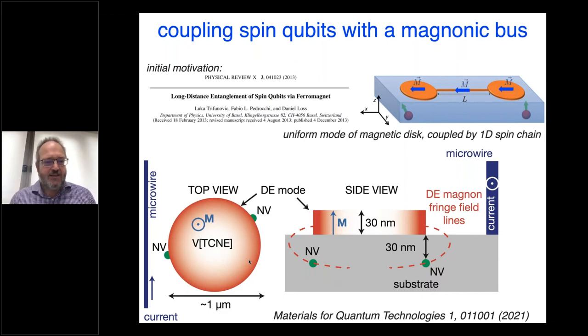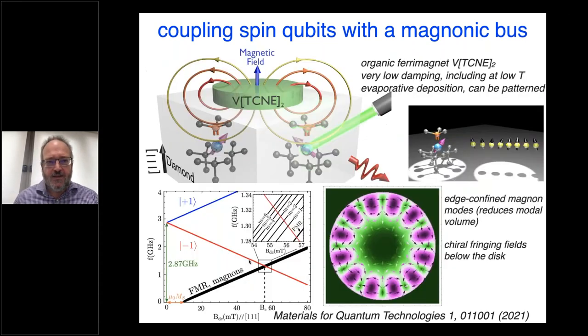So we have a disk of magnetic material with the magnetization out of plane, and that allows us to look at internal spin wave modes of the disk. In the initial proposal, these were all uniform modes. Here we're looking at modes that have internal structure. The reason for that is to take advantage of the lower mode volume for the spin waves in these systems. So in a disk with magnetization out of plane, like below, there are modes that exist along the edge of the disk called Damon-Eshbach modes that are going to be more localized there and therefore have lower mode volume. And when you want to do coupling between, say, a localized spin and a single magnon mode, changing its occupancy by one, that modal volume is going to be absolutely critical.